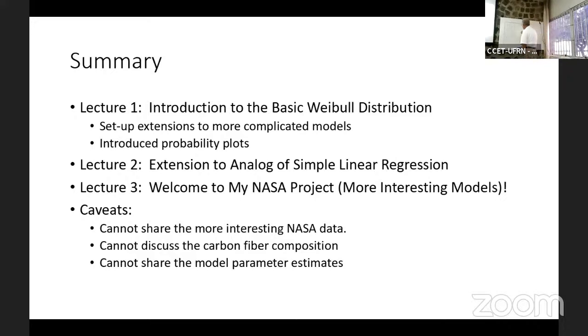No one had ever done an experiment where they could look at the ramp. It was like you had the weight already on the fiber, you kick the stand. So it was viewed as instantaneous load. And then they assumed there was some effective time, because there had to be some time at that load condition. This ramp is very similar to how you do a tensile strength test. That's exactly how we conducted the experiment. We could see at what times they fell.